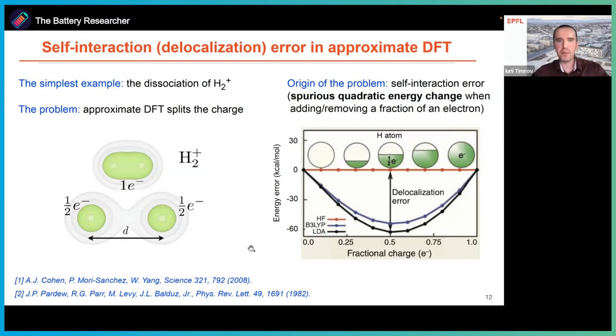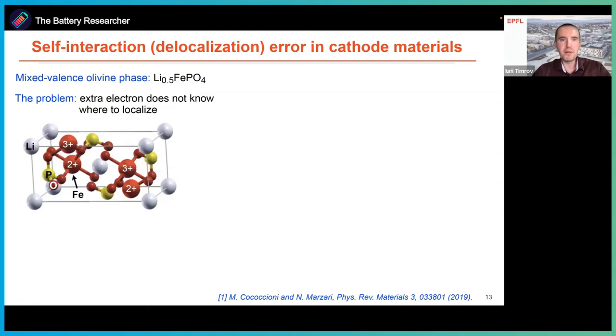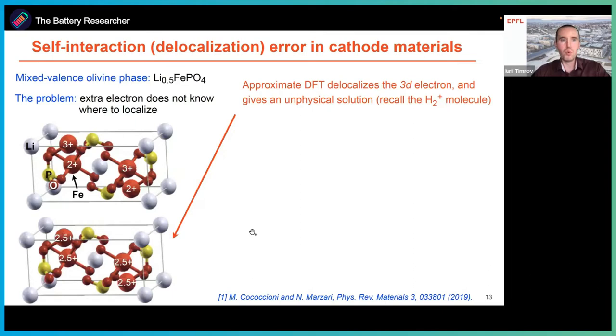If we now talk about a realistic material, in particular a cathode material like the olivine phase at fractional concentration of lithium, 0.5, we also observe exactly the same problem of self-interaction errors. In reality, we have a mixed valence phase where we have iron in two oxidation states, like 3+ and 2+. But if we use DFT with approximate functionals, we have something averaged out, like 2.5+. This happens because the electron which is injected into the system with the lithium ion is delocalized and spread all over the cell. The electron doesn't want to localize on one particular iron, but it spreads out and equally distributes everywhere, which doesn't make any sense.